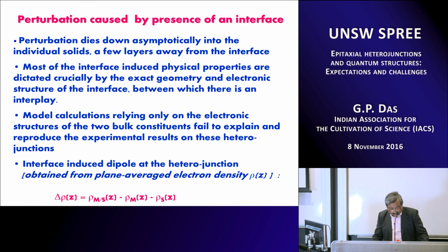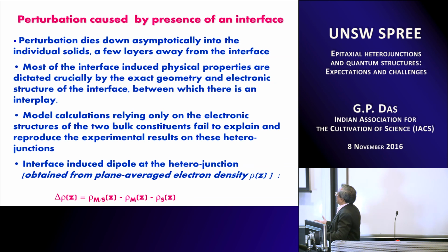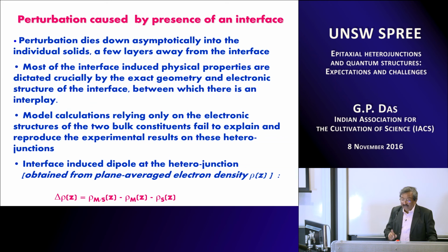Whatever you are seeing here, this delta rho is what you get when you subtract the rho of the metal semiconductor junction and the two individual rho, meaning the charge density, the electron density for the metal and the semiconductor. So when you subtract the charge density of the metal and the charge density of the semiconductor from that of the metal semiconductor interface, you get the delta rho, which is responsible for calculating the interface induced dipole, and this is very, very important.